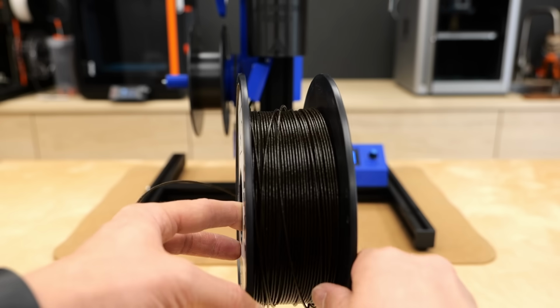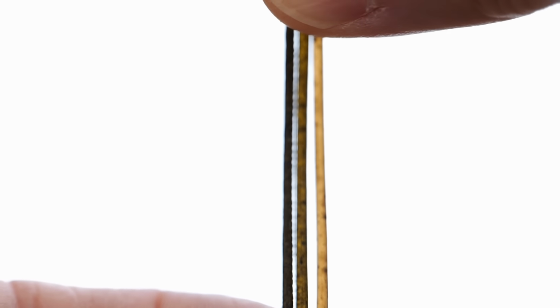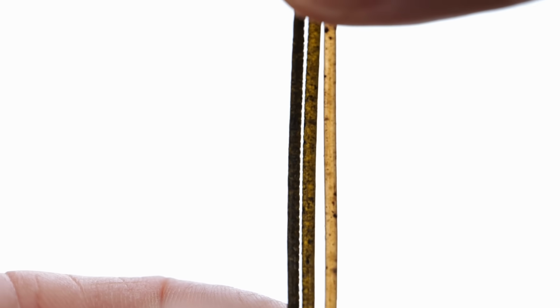If we put the first 3 attempts side by side, we can see something very interesting. The PLA from pellets had the lightest color and was still a bit transparent. The re-extruded filament was already darker, and I previously suspected that the sugars caramelized. Yet the filament made from the PLA powder was actually even darker, which hints that the change in color is simply due to a better distribution of the particles within the filament. Pretty impressive, to be honest.